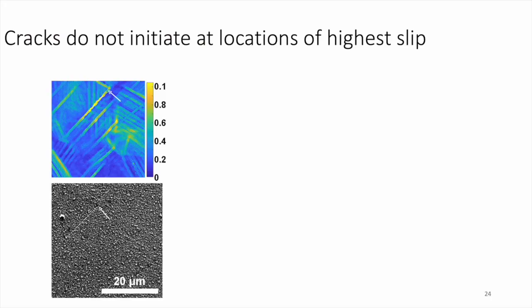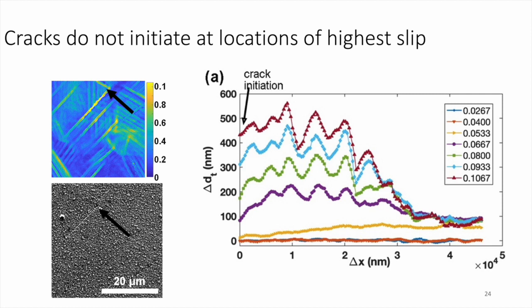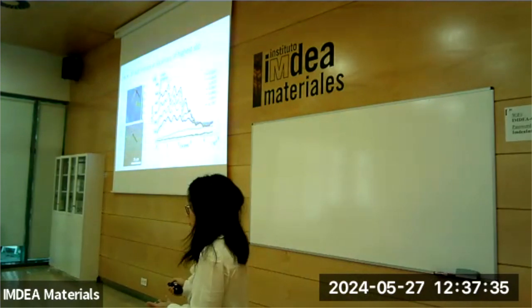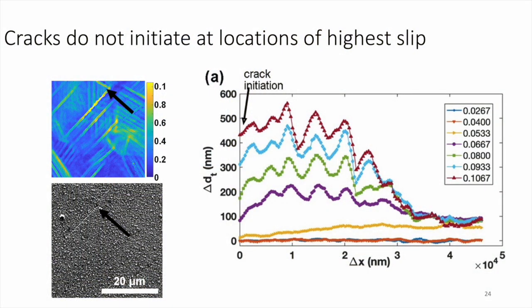If we take this particular boundary, this is where the crack initiates. And if we plot the slip value along this slipping boundary with different tensile elongation, we found that, first, as the elongation increases, slip value increases. Second, we can see here we have the highest slip value. Here is where our crack initiates. Our crack does not initiate at the location with the highest slip. So we performed this analysis at multiple locations along all of the slipping boundaries for different tensile elongations for all of the samples. For each sample, we have at least 600 points of interest for analysis, and we found the trend to be consistent. So where does it initiate?